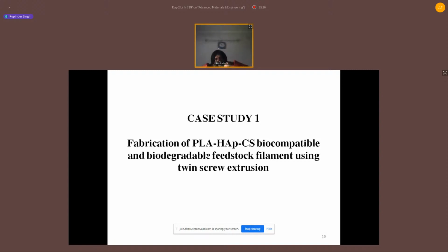So that spacer must be there for a period, till the full bone growth is there, right? So once the bone growth is there, I have to remove that spacer, right? So that is the requirement. For this purpose, we are using PLA as a matrix, because PLA is biocompatible and of course biodegradable. So we are interested in finding a situation in which, at the same rate at which my bone is growing, the spacer that I am putting mechanically in between must dissolve. Since PLA can dissolve, I can use that as a spacer.